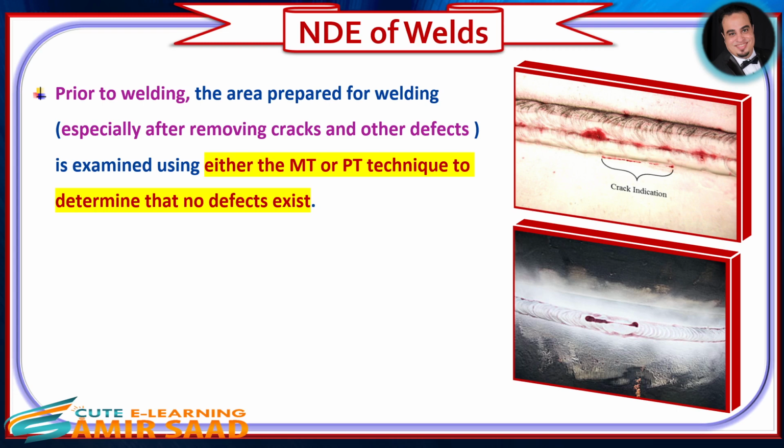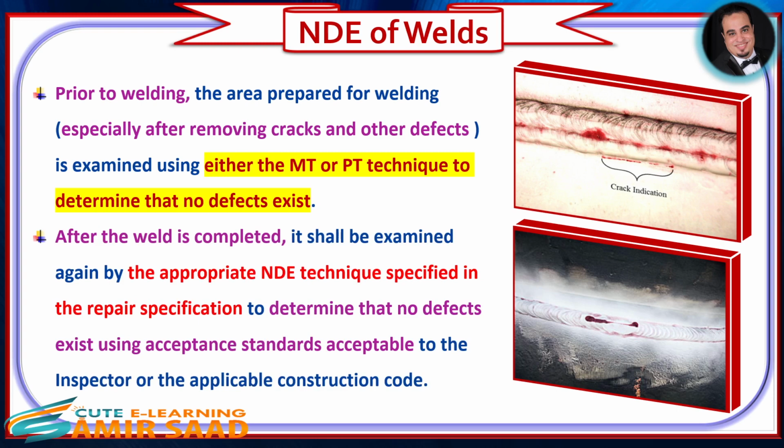NDE of welds. Prior to welding, the area prepared for welding, especially after removing cracks and other defects, is examined using either the MT or PT technique to determine that no defects exist. After the weld is completed, it shall be examined again by the appropriate NDE technique specified in the repair specification to determine that no defects exist, using acceptance standards acceptable to the inspector or the applicable construction code.